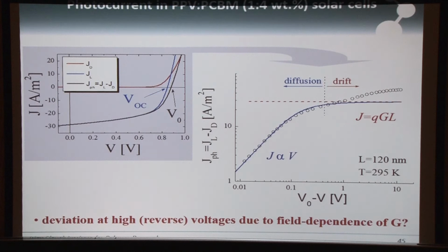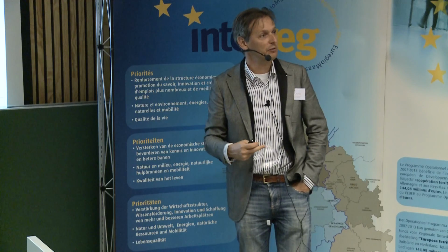But what we do basically, we change the normal measurement. We take this point as our new origin here. And then when we go like this, in our case we go like this. So this means 10 volts here means almost minus 10 in reverse. So we plot V0, it's this point minus V. So we rotate this picture by 180 degrees. And the reason why we do that is that now we have the current in the solar cell as a function of the electric field in the solar cell. And then we can compare it with Goodman and Rose.